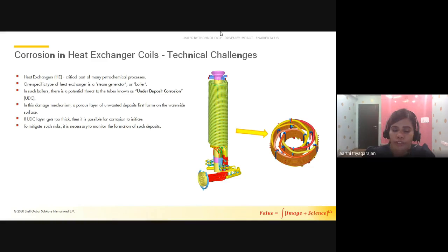In the plant, out of 36 SEC coils, two of them were inspected every quarter with microscopy image analysis, which is nothing but a destructive method, and both samples were used. The inspection was achieved without affecting the production. However, the remaining 34 coils were inspected via non-destructive, or NDT, methods. These SEC coils were damaged because of an underlying mechanism called underdeposit corrosion, which is nothing but solid deposits that are formed from specific ions in the water.